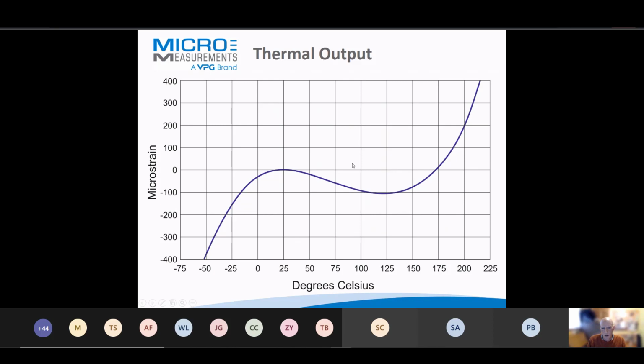So if you're doing laboratory tests, you will have no measurable thermal output. If you do happen to change temperature, let's say to 100 degrees Celsius, you can see here we're somewhere around minus 90 microstrain, and this curve is published with every pack of gauges. So you can plot this in an Excel spreadsheet or in your instrumentation for automatic correction.